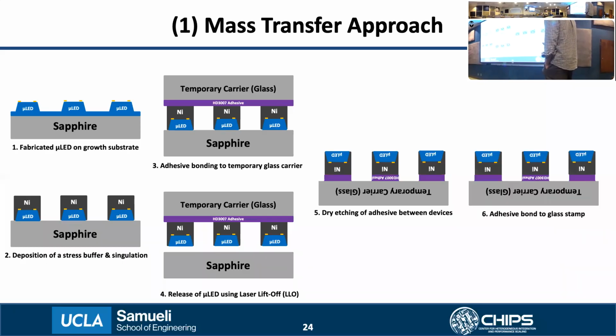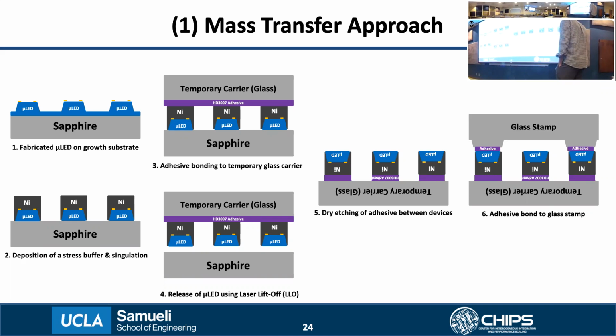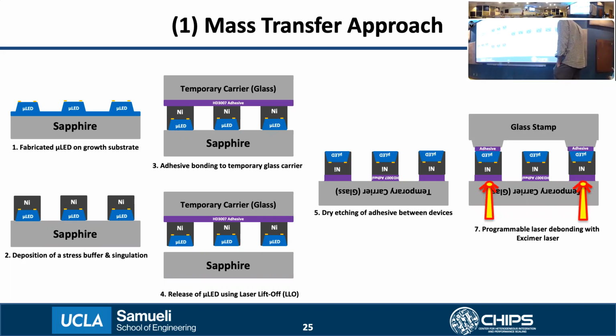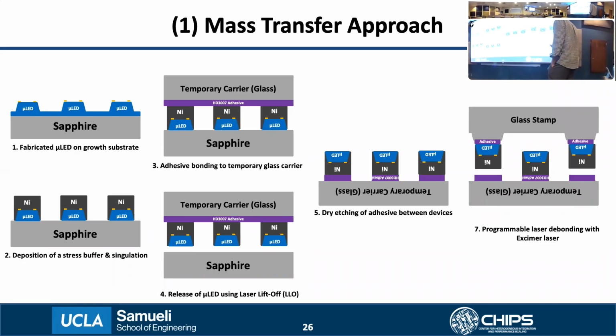And then we can do our mass transfer step on this sample, wherein we have these LEDs sitting on the temporary carrier face down, and we bond to it a glass stamp with adhesive on it to selectively bond to those LEDs we want to pick up. And then we do a programmable laser debonding with an excimer laser to the backside of the temporary glass carrier, so as to detach only those LEDs that we want to transfer to the stamp,